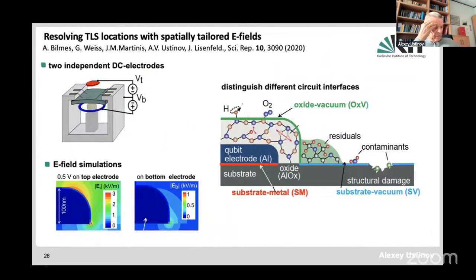So the next thing we were interested in was trying to find at which surfaces these defects occur. They can occur, for example, at the interface between the dielectric substrate and the metallic electrode, which is basically the superconductor. They can occur, as I mentioned, on the surface of the qubit electrode in the oxide layer formed naturally on metallic aluminum. And they can occur also on the outer surface of this oxide, which has just vacuum on the other side. They can occur at different distances from the edge of the superconducting film along the substrate, where defects will still experience the alternating electric field of the qubit, which of course will decay farther away from the sample.